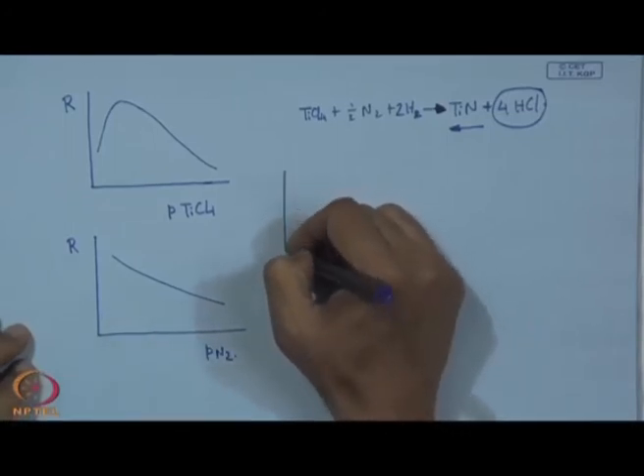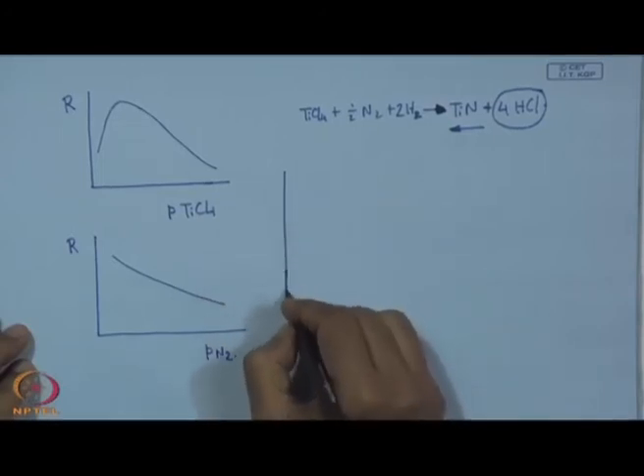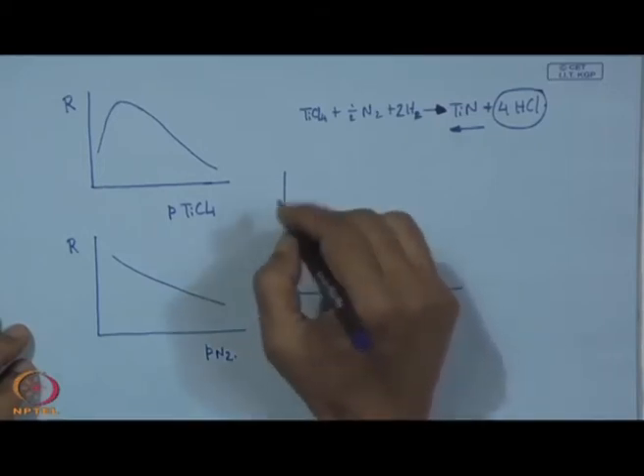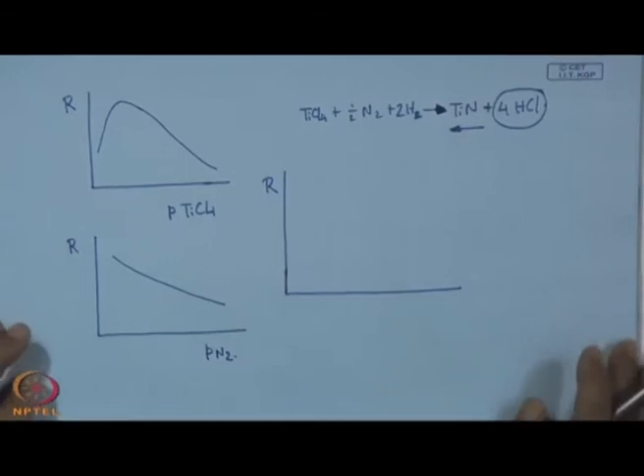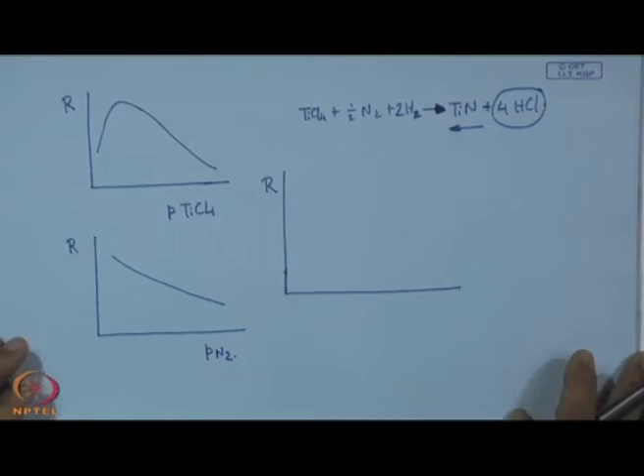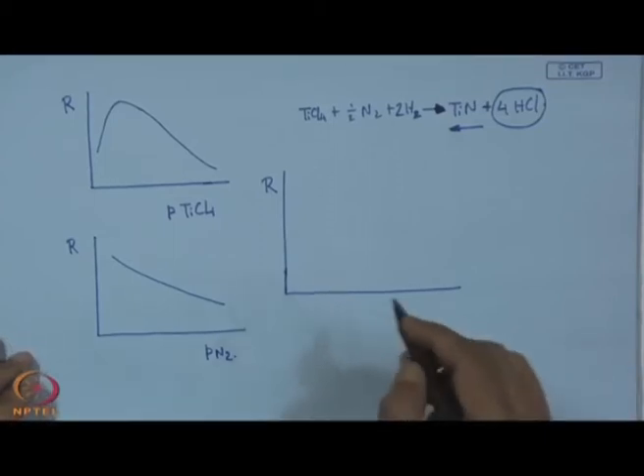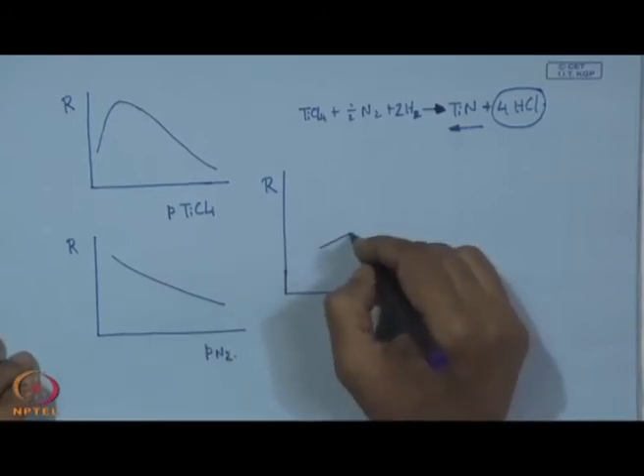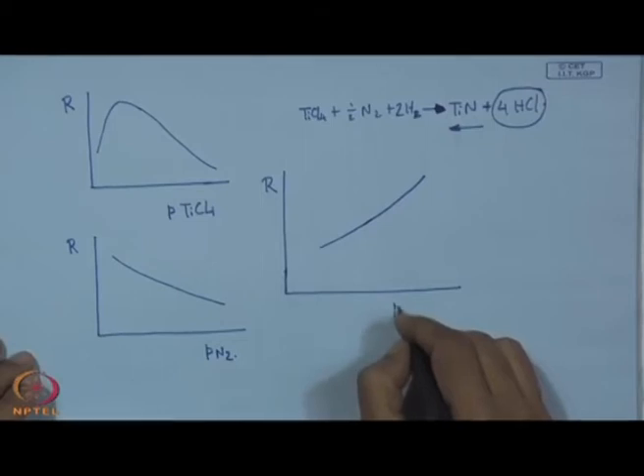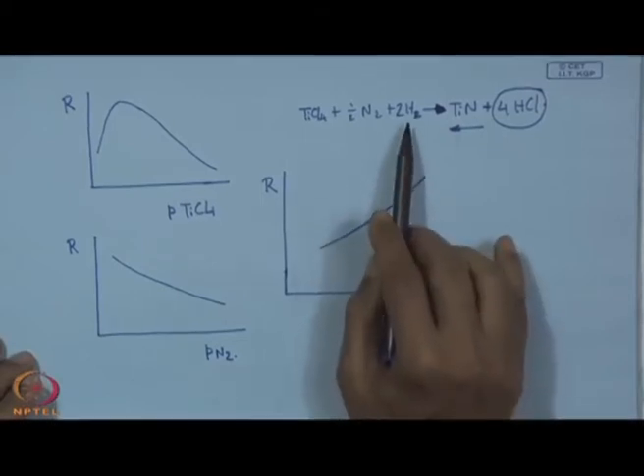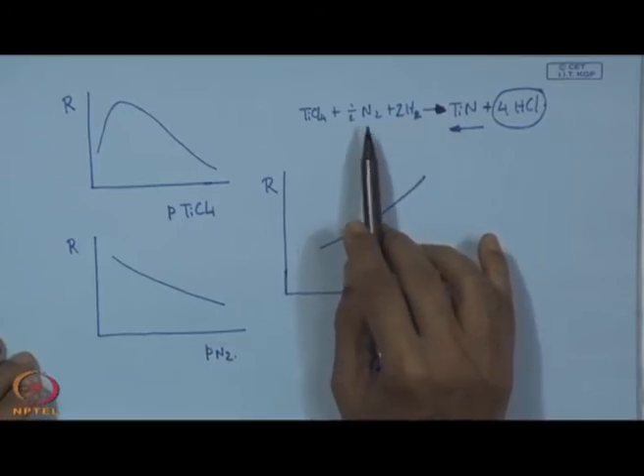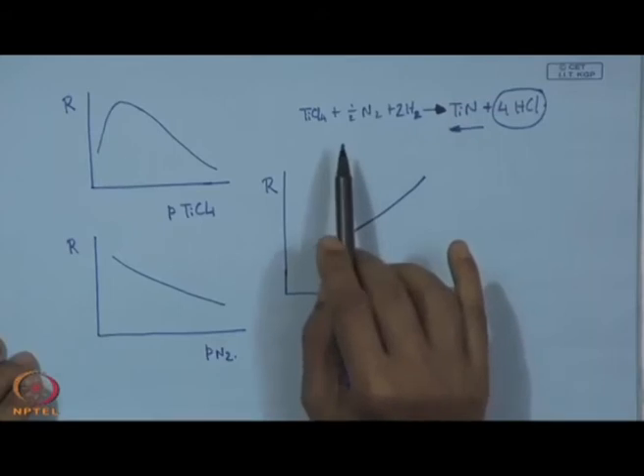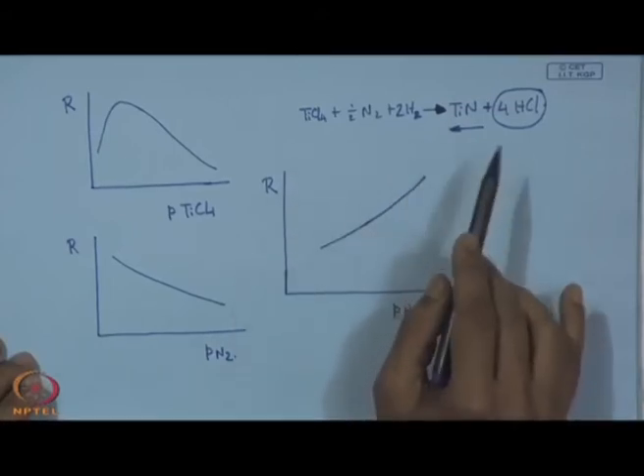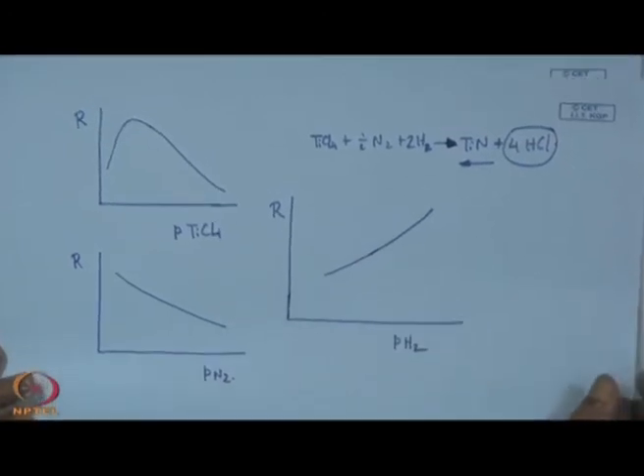However, if we increase hydrogen under the same condition, then what we find is that the growth rate, which may be so many milligrams per hour per unit area of the substrate, or simply microns per hour, that is the thickness of the coating, shows a rising trend. It is simply because hydrogen has a better reducing effect, and if we have excess hydrogen, then this reaction is going to move in the forward direction, and as a result we have a rising tendency.